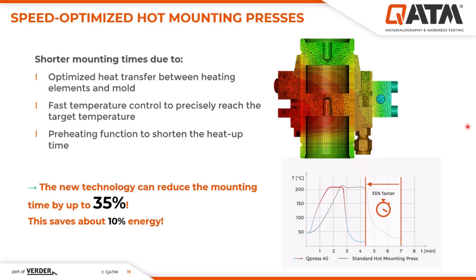Another way to shorten mounting times is by using modern hot mounting presses. With the help of thermal simulation, both the machine design and the temperature control can be optimized according to the latest technology standards. In addition, new machines feature a preheating function that allows the press chamber to be preheated before the process begins, further reducing the heating phase. Overall, this can reduce the mounting time by up to 35%, while also lowering energy consumption by approximately 10%.